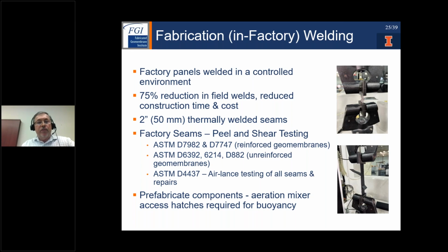Fabrication, the in-plant fabrication is very important for these digester covers. And here again, we're doing factory welds under a controlled environment. By doing this, we often see a 75% reduction in the amount of field welding, which results in reduced construction time and cost, and overall better seam integrity. We typically are using a 2-inch factory seam, similar to what we use in the field, a thermally welded seam. And all of our factory seams are tested in peel and shear testing in accordance with the appropriate ASTM test method, whether we're fabricating a reinforced or unreinforced material. And as well, we try to prefabricate as many of the surface cover components as possible, including things such as the aeration mixer and access hatches, which really do require positive buoyancy, as Steve pointed out.